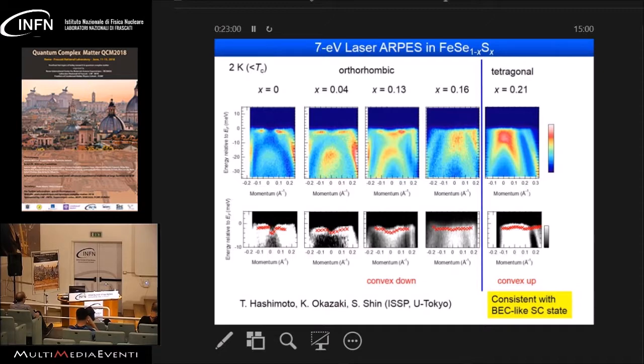But if they blow up this low energy part, what they found is that we can still see a convex down feature in the orthorhombic phase. So the minimum gap occurs at kF. But if you go to the tetragonal side, it shows a convex up feature, okay? So this is, again, consistent with the BEC-like state in this tetragonal side of iron selenium sulfur.